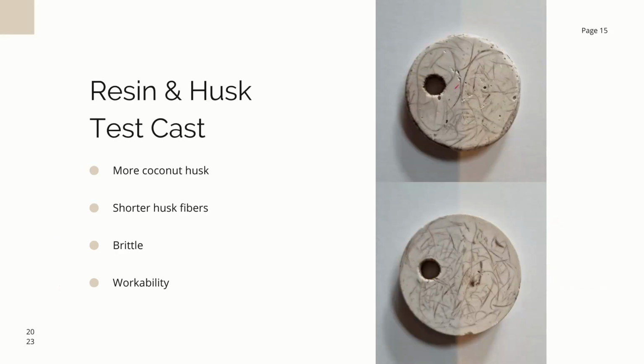The first test cast focused on testing the casting properties of the coconut husk mixed with the resin. The findings of this cast showed the need for more husk to improve the strength properties of the material, as well as shorter husk fibers to improve the spread of the fibers throughout the mold. The prototype material proved to be brittle, but still held its shape, allowing for good workability regarding sanding and cutting.